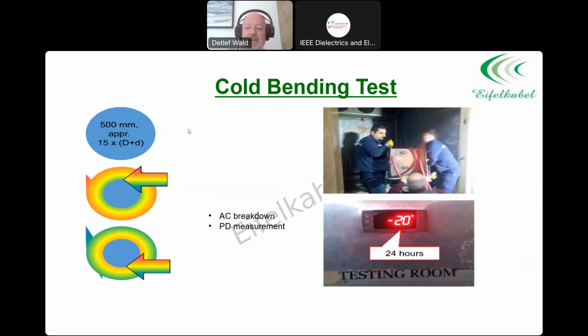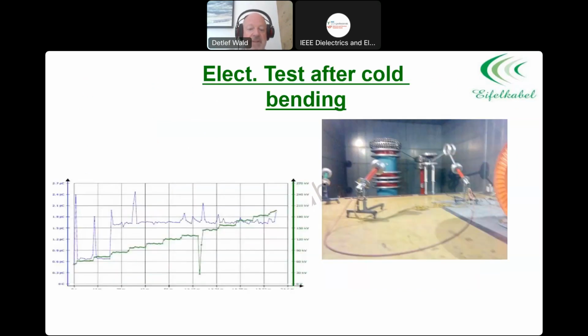However, as you can see here, these two nice guys, they made a test. What we did, we put a cable around the drum, it's 15 x (D+d). We left it for 24 hours at minus 20 degrees, and then we unwound the cable, and afterwards we made an AC breakdown test and a partial discharge measurement, and none of these tests showed any significant damage to the cable. At minus 20 degrees, it was quite stiff, but we managed it, so you can handle and install the cable at minus 20 degrees. So low temperature is not an issue.